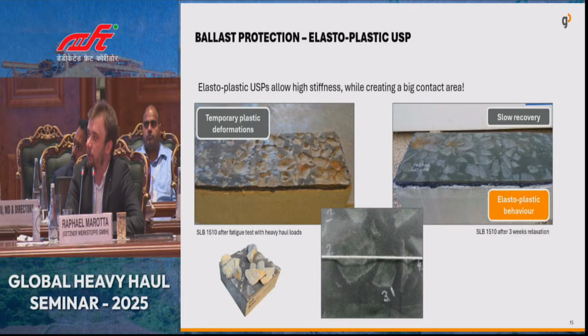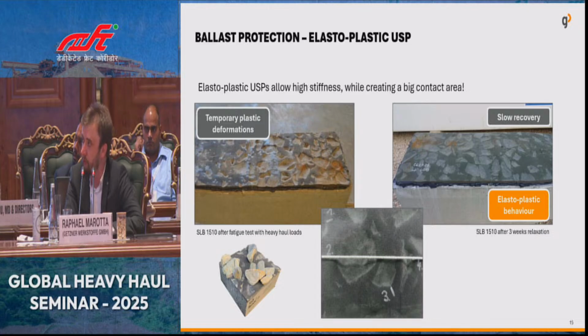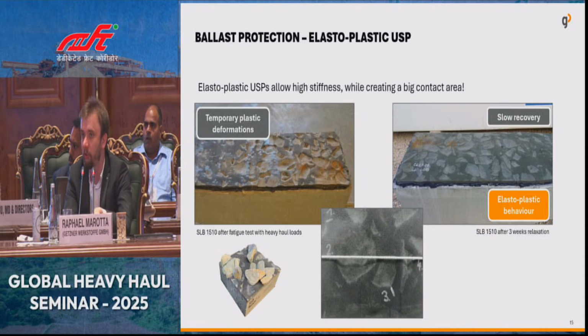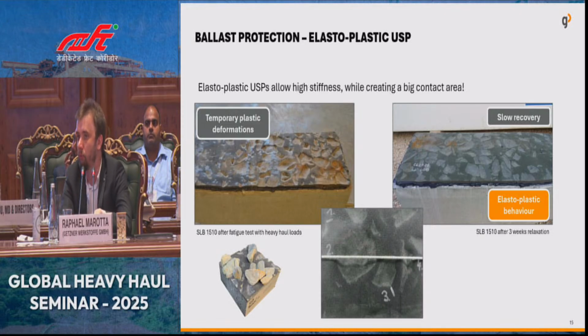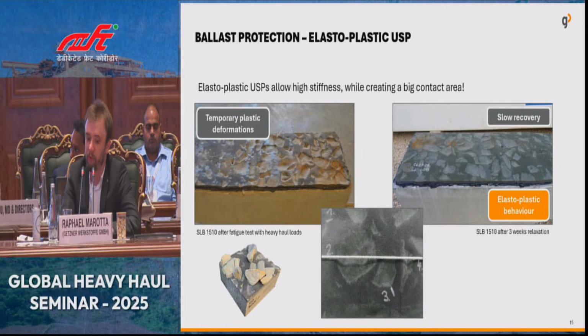That's a key feature, a key characteristic of our products. This is the elastoplastic behavior. You see that when the undersleeper pad is subjected to higher loads, it experiences some deformation, but after a while, you see this slow recovery. That means that the undersleeper pad is not damaged, even when subjected to the axle loads that I mentioned previously, with that extreme annual tonnage. This does not result in permanent damage to our products, and that's what sustains the performance over a long period of time.